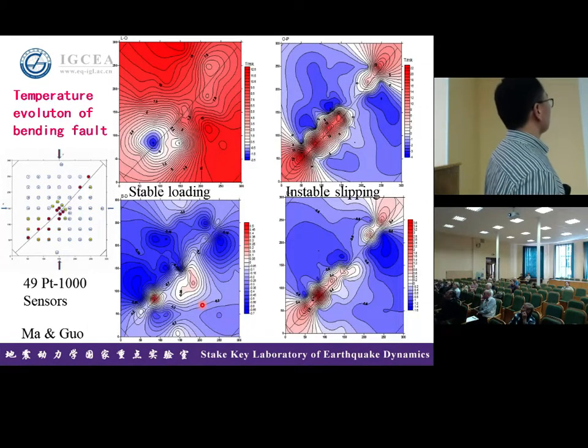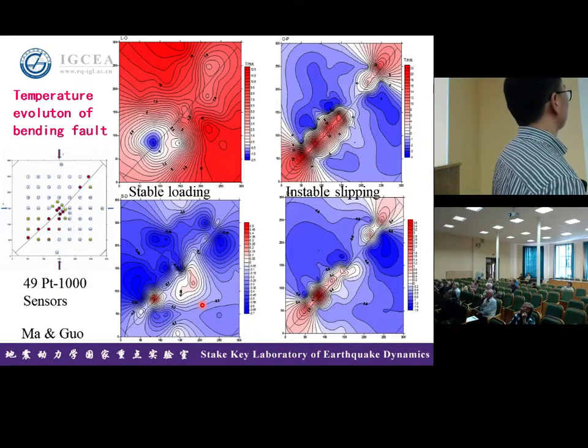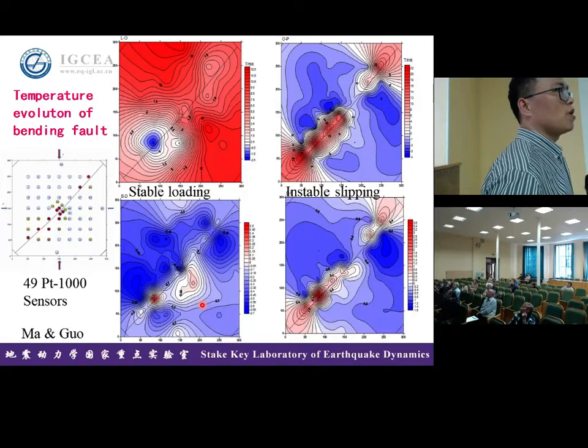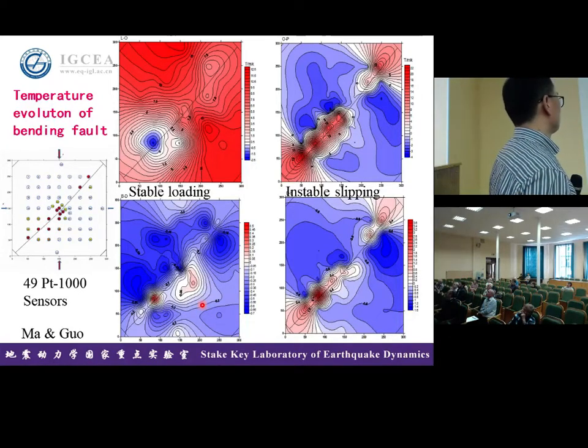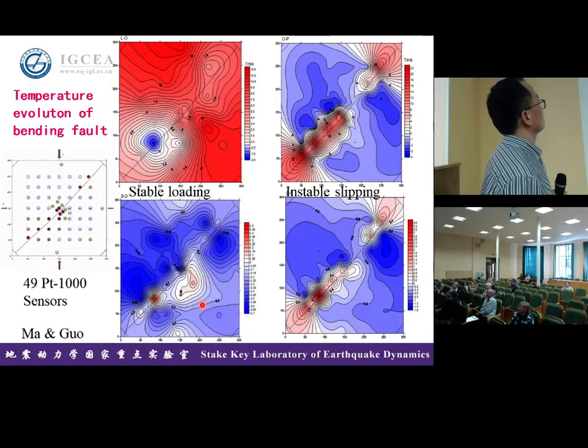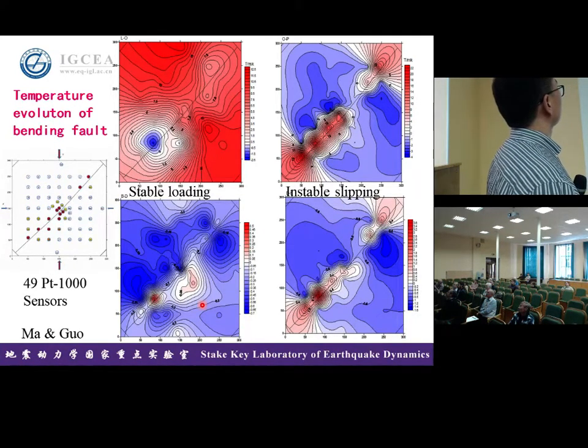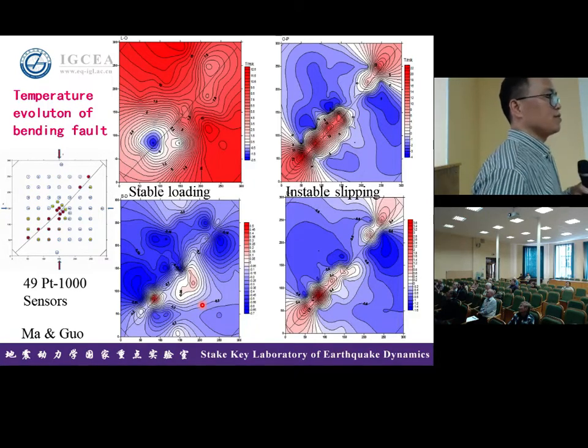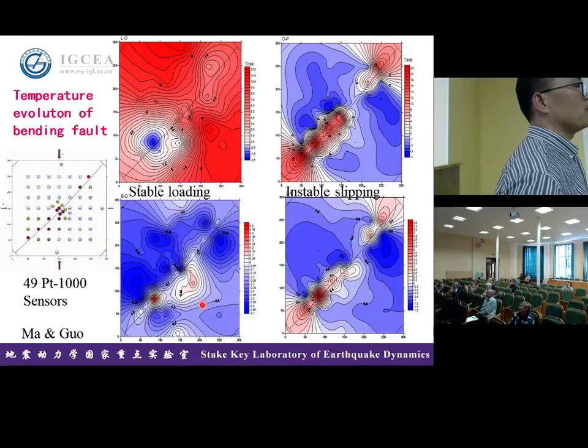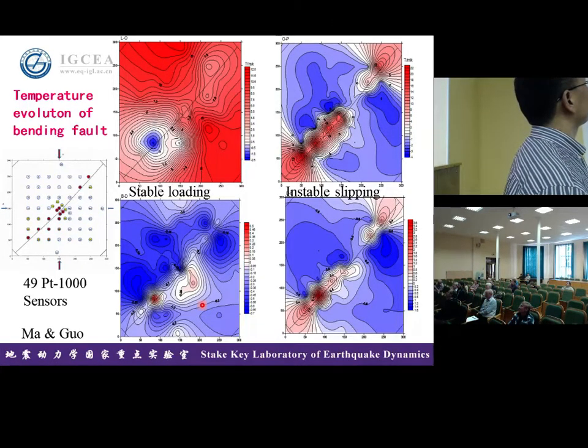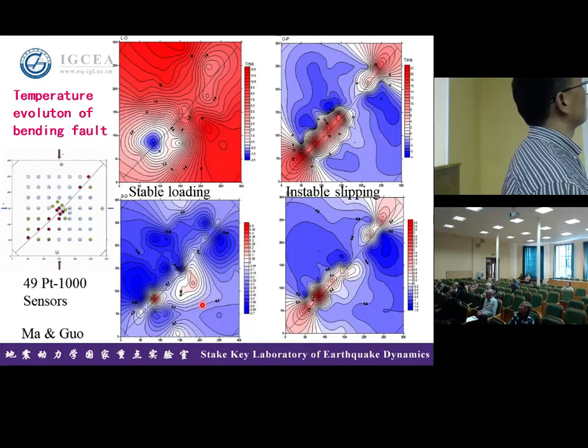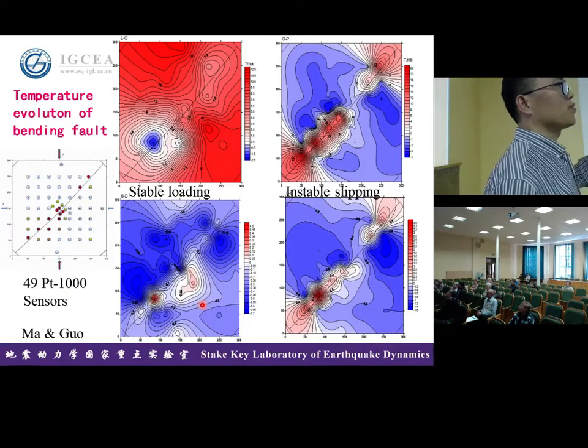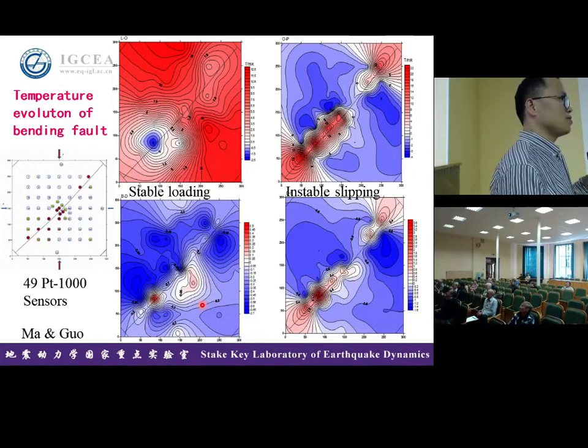And this picture shows us the temperature evolution of faulting. We pasted about 49 PT sensors along this area. We will find that in the first stage of loading the sample, the temperature of the sample increases with loading, and when the fault slips, the temperature along the fault increases very fast, but the level is so small.